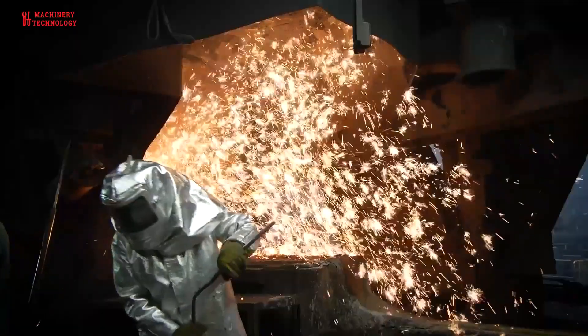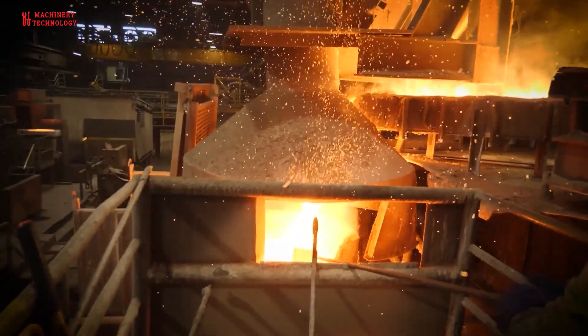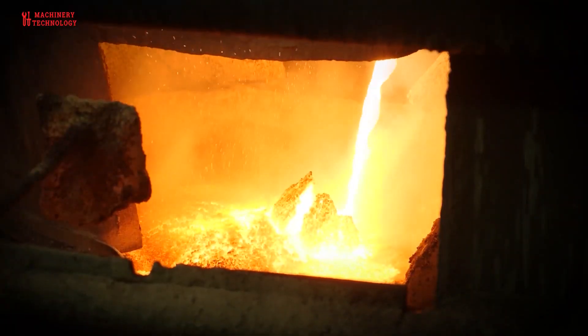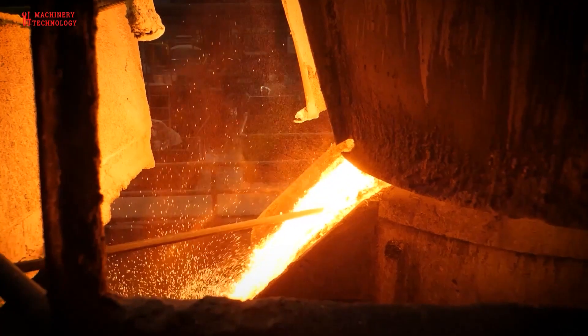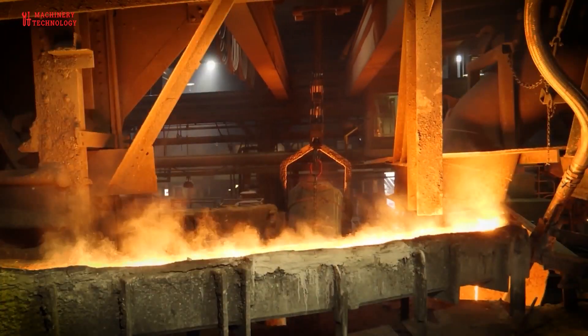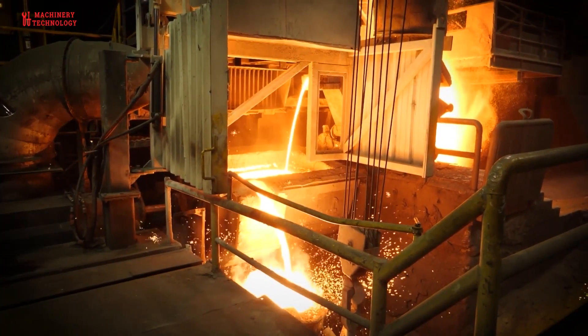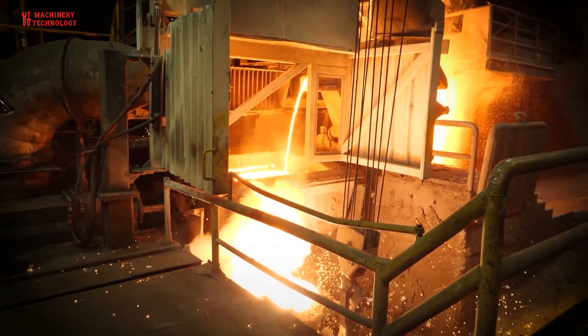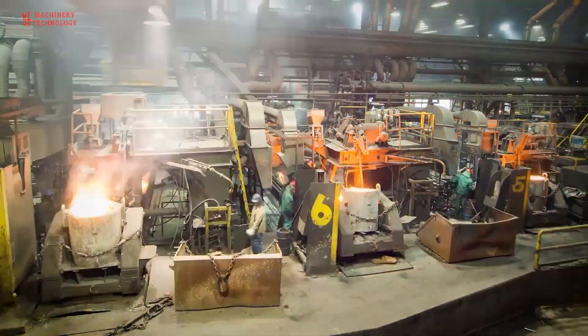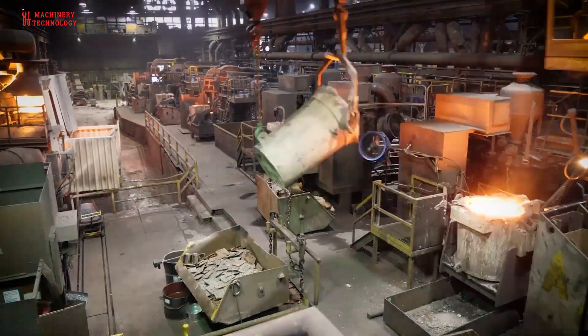The recycled metal is sorted and lifted into the furnace called the cupola. The cupola is a large steel cylinder that melts the metal into molten iron. The 2,800-degree molten iron flows out of the cupola and into a series of ladles. The desulfurization ladle removes some of the sulfur to bring it down to the levels needed to change the gray iron to ductile iron. The transfer ladle holds the iron until it is ready to be transported to the different casting machines. Magnesium is added in the transfer ladle, which starts the process of transforming the metal from gray iron into ductile iron.